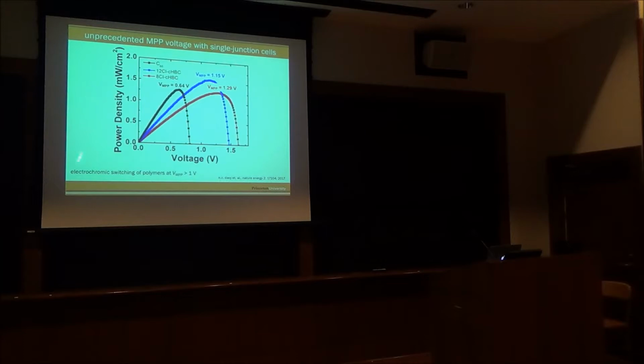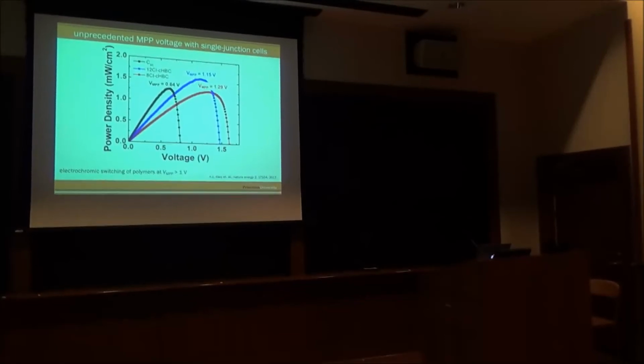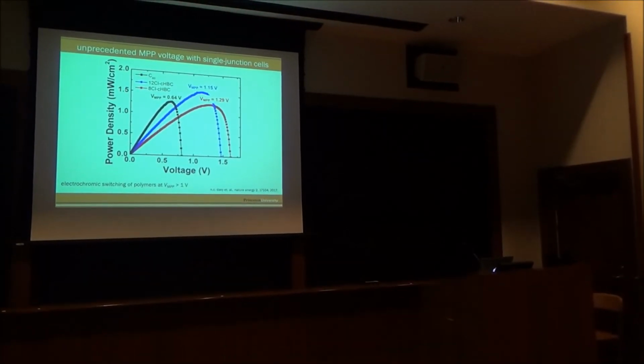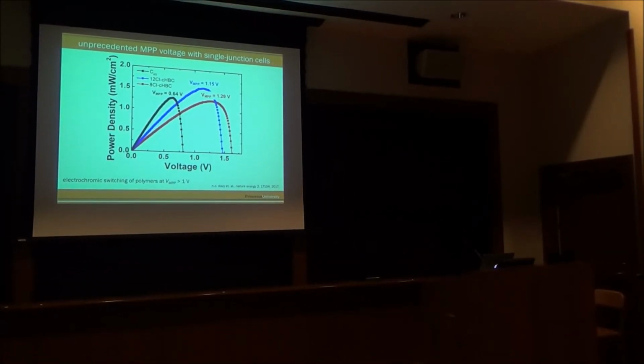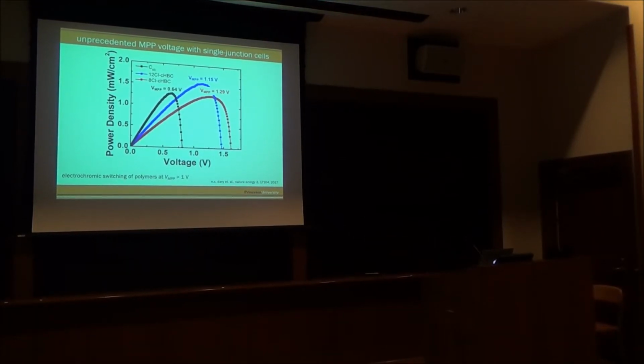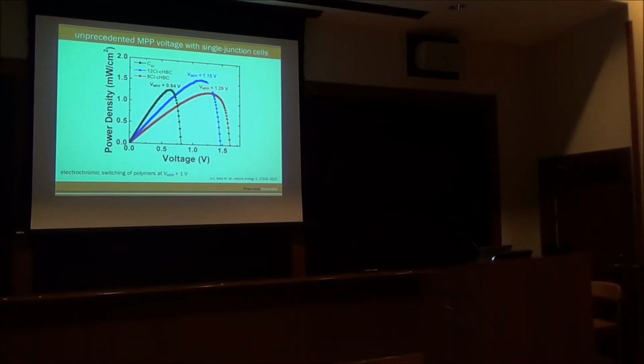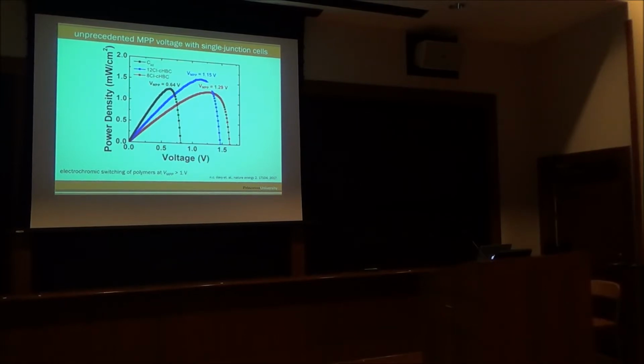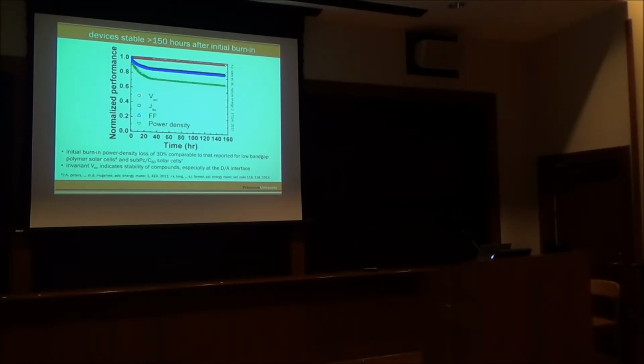You can look at power density as a function of voltage. This tells us the quality of the power that we're getting. With a C60 device, we're getting a power of about 1.2 milliwatts per centimeter squared, and this power has a voltage of 0.64 volts. But with our cells, we're getting comparable or slightly higher power, at much higher voltages. And this voltage is nice because we can use it to modulate the switching of our electrochromic polymer.